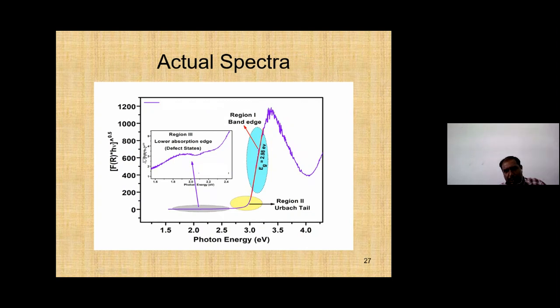This is one more spectrum which we have shown. The first thing is that you can basically divide this optical absorption spectrum into 3 parts. One, the sharp absorption is due to the band gap. The tail region will give you the Urbach tail states, which is essentially the electronic disorder present in your lattice. And then you have the lower states, which are essentially due to some type of vacancies or defects present in your samples. So these are the 3 very powerful pieces of information which you can get.